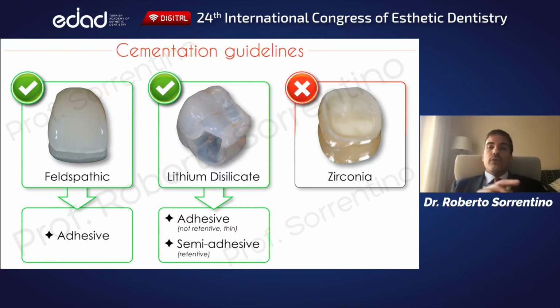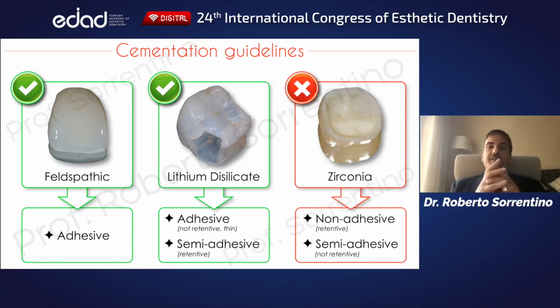However, no univocal guidelines can be drawn for zirconia, as nowadays conventional luting agents are considered the gold standard, but simplified resin cements could be useful in case of insufficient retentiveness of preparations. Thus, caution: to date, zirconia cannot be considered a first choice material to cement purely adhesive restorations.